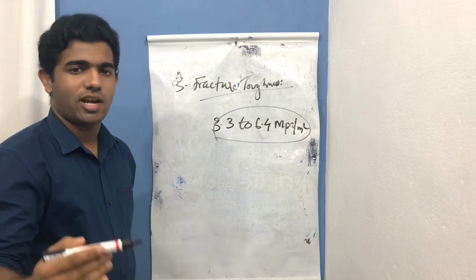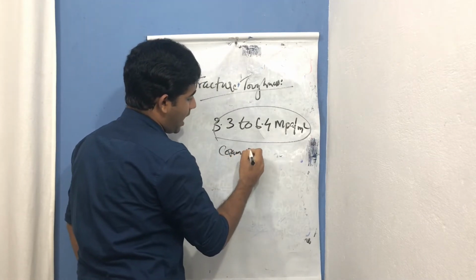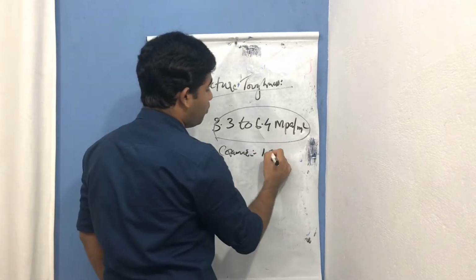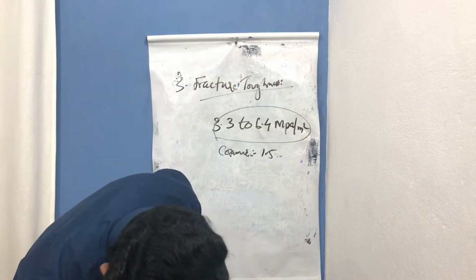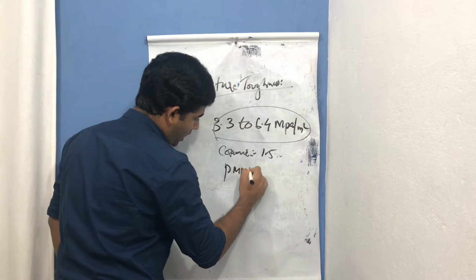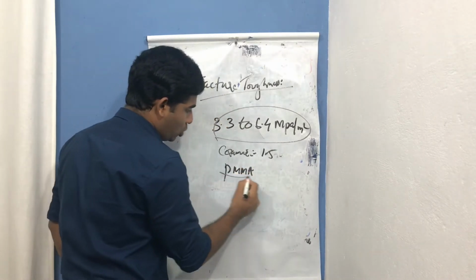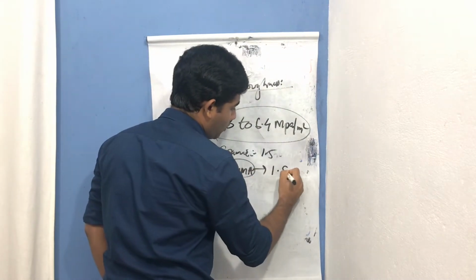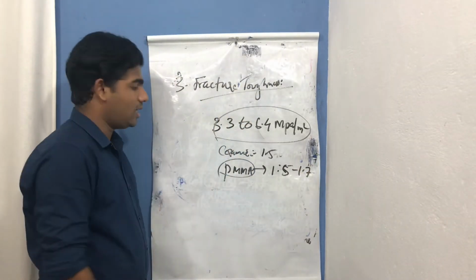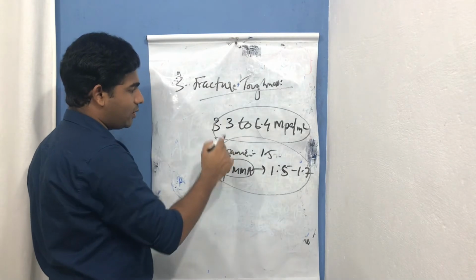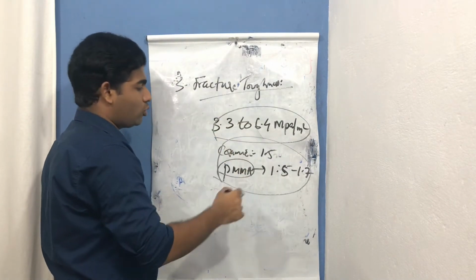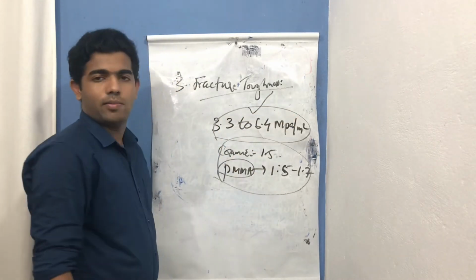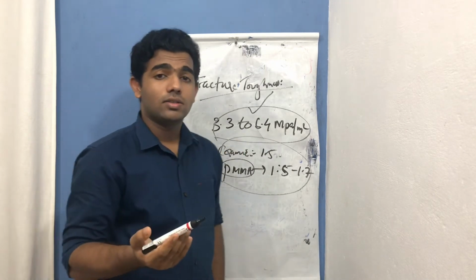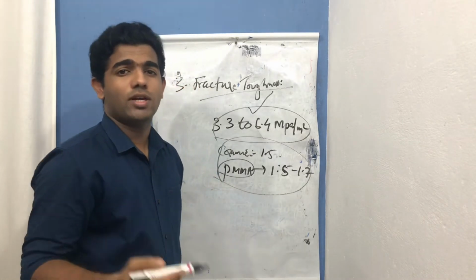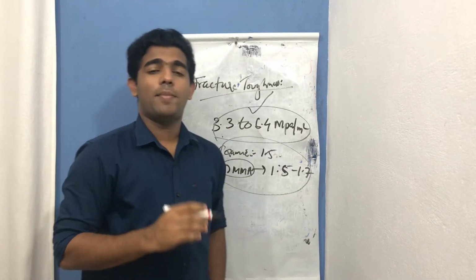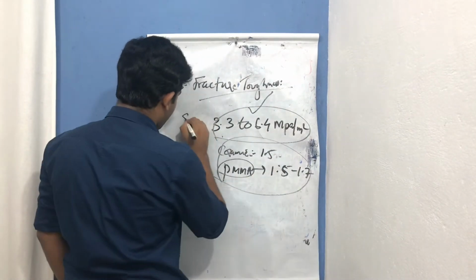How can you relate it to a real life scenario? For example, the ceramic that we use has a fracture toughness of only 1.5. Whereas PMMA, polymethyl methacrylate, which is used in our bone cements, has a value of 1.5 to 1.7. See, when you use an artificial substance to replace the bone, the bone actually has this property in a higher amount. That means the fracture toughness of our natural bone is higher than the synthetic or artificial ones that we use, that is 3.3 to 6.4 megapascal per meter square. Whereas steel has about 70.